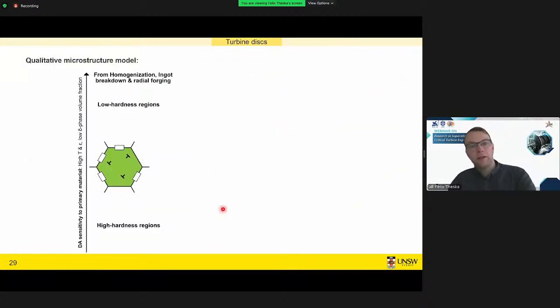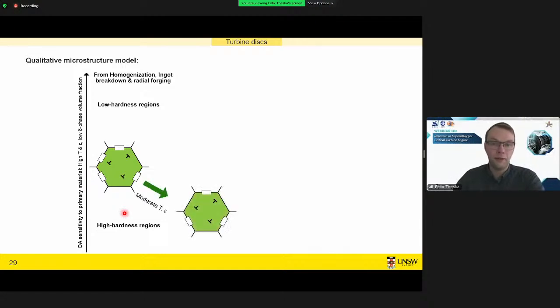Now we can go back to our microstructure model and adapt this for the situation in directly aged turbine disks, where we start again with this gamma matrix with a lot of dislocations and a little delta phase on the grain boundaries. And these turbine disks are really complex, so that the local temperature and the local strain that are induced can vary significantly. In this case, the high hardness region experienced a moderate temperature as well as a moderate strain, so that not much has changed in this case.